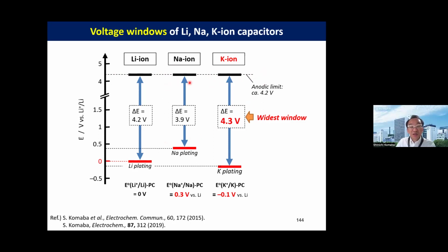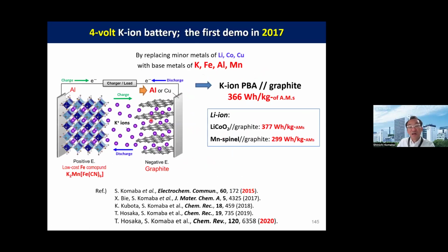In the case of sodium, because of the higher E0 of sodium deposition, there is a little bit narrower potential window for sodium. However, in the case of potassium, because of the lower potassium plating potential, we will see the widest potential window compared to lithium. This is very, very good news for having a higher voltage battery based on the potassium ion system.